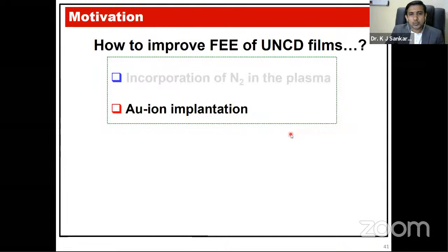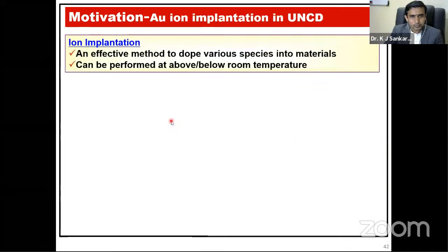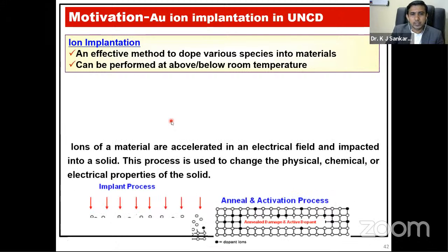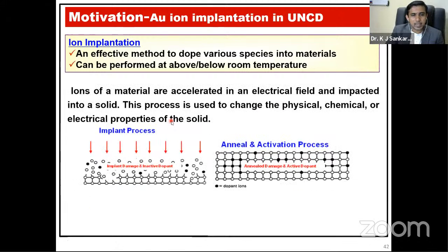So now I would like to focus on the field electron emission properties of the UNCD films using gold ion implantation. Why do we need implantation? Because implantation can be achieved at a low temperature, even at room temperature, but the nitrogen-grown UNCD films need high temperature. And we can also dope various species inside the materials, so that we can do implantation very easily to get highly conducting UNCD.